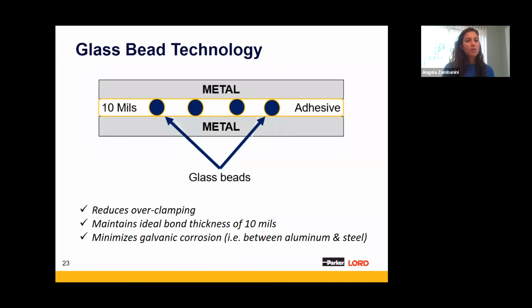So now the difference with LORD Acrylics is our glass bead technology. And we suspend glass beads in our materials for 2 reasons. One, to reduce over clamping. No matter how hard you clamp down, you're not going to squeeze out all the adhesive in there. So some issues that maybe newer customers or newer shops run into is they'll have somebody come in with Popeye arms, really, really strong, clamps it down as hard as they can, and then they squeeze out all the adhesive that they just laid down. And then the part fails and they wonder why it failed. Well, because there's no adhesive in there holding anything together. So we put glass beads within our material so that you always get that ideal bond thickness.